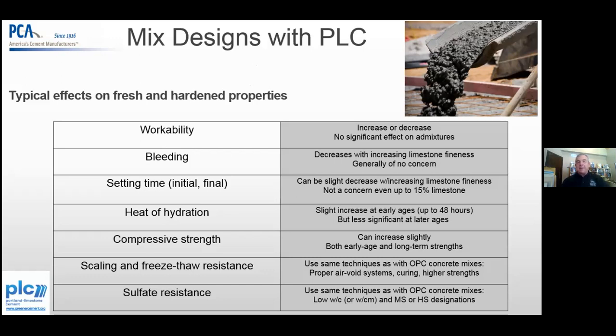better, they say. Set time, there might be a slight decrease in set time, only because you're optimizing your particle packing, your particle fineness. Limestone fines filling the gaps between Portland cement particles. Heat of hydration, we really haven't seen it. We thought that we'd see an increase at early ages, but it's really not that measurable, and it's not that much of a difference. So you can use it in mass pours, similarly to Portland cement.